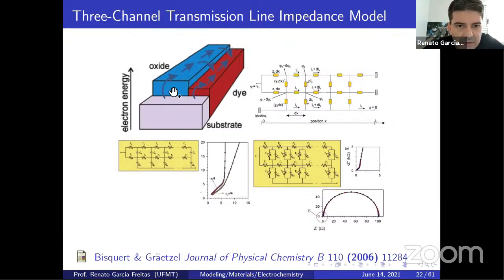So Grätzel and Bisquert suggested titanium oxide with a dye, in which we have an oxide which injected on the dye. And the level of the conduction band and valence band was pretty different. So they considered 3 lines in this case. One line from this one, and from the electrical one. So we have the resistance, this line here, another part related here, and this part here. So we have the impedance, so transmission line here, and 3 line channels like this one. So we have observed species, transmission, charge transfer here, another charge transfer process here.